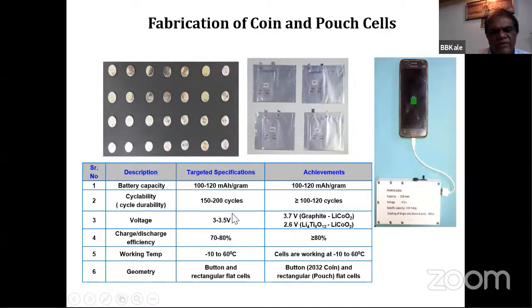And we use carbon as well as graphite, you can see 3.7 volt, and lithium titanium oxide we generally use 2.6 volt maximum, but stable is 2. Then efficiency we observe is almost more than 80%. Working temperature is -10 to 60. Now we are trying still lower temperatures. Geometry, we have button cells, rectangular flat cells. So we can make 2032.